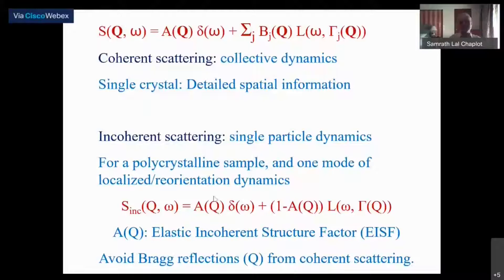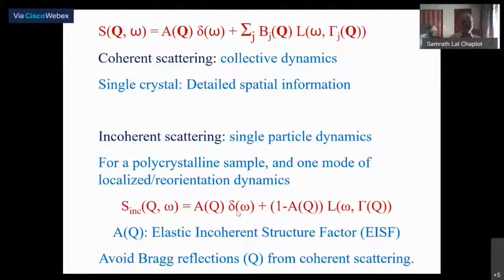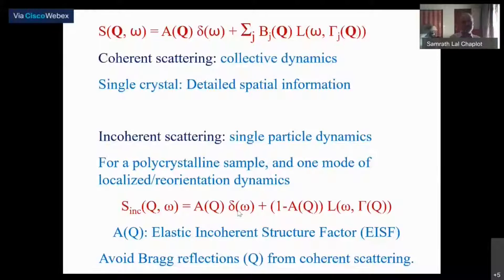When we look at incoherent scattering in the presence of other atoms which are coherent scatterers, there will be Bragg reflections. Bragg reflections are very strong and very intense, and in their presence it is difficult to see the quasi-elastic signal which is usually weaker. Therefore we avoid wave vectors exactly equal to or very close to the HKL or the reciprocal lattice points. Away from that there is no serious problem, and in general these functions are fairly slowly varying as a function of wave vector.